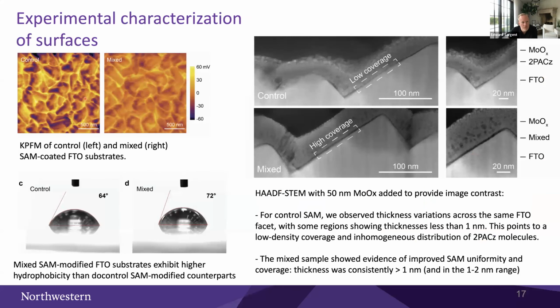Experimentally, we saw quite a bit of evidence that these benefits were being accrued. From Kelvin probe, we see a better spatial uniformity for the mixture of molecules compared to the control case. From wettability, or wetting angle, you'll see that we see a higher degree of hydrophobicity when we use the mixed SAMs. And then we did a microscopy study to try to look at the gap between the underlying FTO and a layer that we put on artificially, this was moly oxide, to provide for contrast and therefore to provide for the ability to estimate the effective thickness of the monolayer.